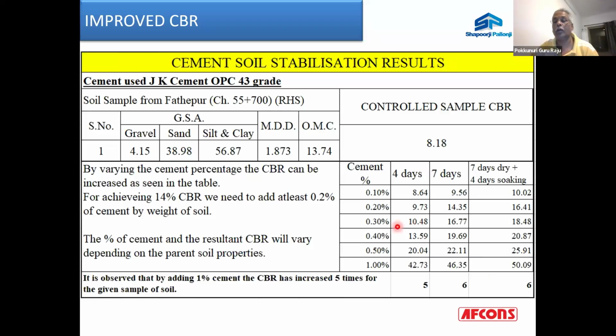So what we normally do in the field is, if my expected value is say 18, and I'm adding say 0.3%, I know on the 4th day I'm getting 10. So even if I'm getting only 10 after the 4th day, immediately after the fourth day I can start using this layer for the next layers, because 8% CBR is good enough to take loads of loaded vehicles. Because generally we design based on 8% CBR also. So that is the bare minimum thing we generally keep in mind when we do soil stabilization.